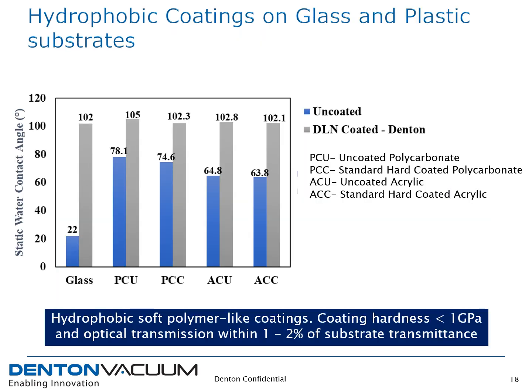Using lower ion energies, we can coat soft polymer-like coatings. These are hydrophobic coatings and have very good adhesion to the substrate. What I have shown in this bar chart is a comparison of the water contact angle of the coated and uncoated substrates. Several different substrates were tested, and in all cases, a water contact angle greater than 100 degrees was obtained, both on glass and plastic substrates.